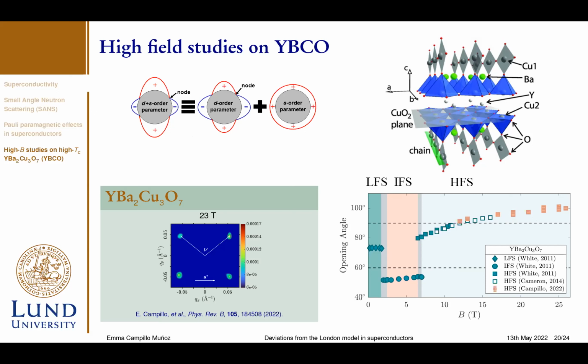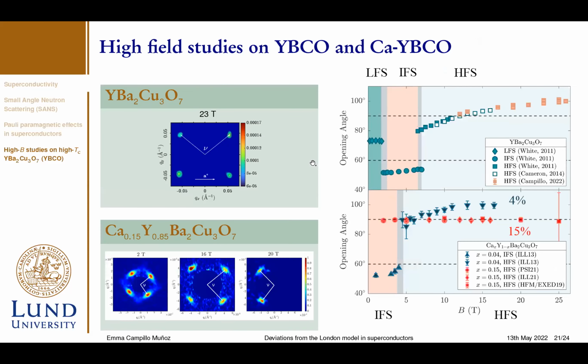Since the superconductivity is controlled by the planes and the chains, we can also control these contributions by adding calcium to the sample. Once adding calcium, we are adding to the concentration of holes in the superconductor, which means that the superconducting properties will be changed as well. As in the case of YBCO, we were able to measure the vortex lattice on a 15% calcium doped YBCO sample up to 25 Tesla. However, on this 15% calcium doped sample, we were not able to observe any transition, and we think this is because of pinning effects.